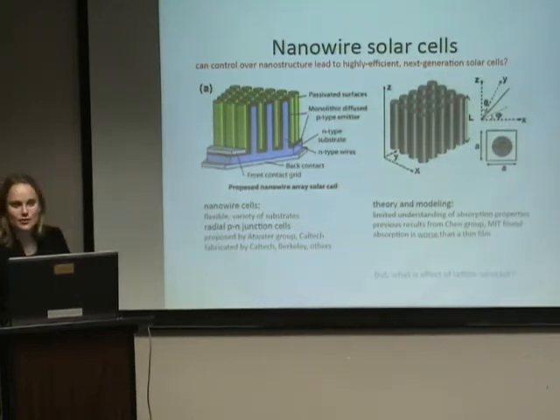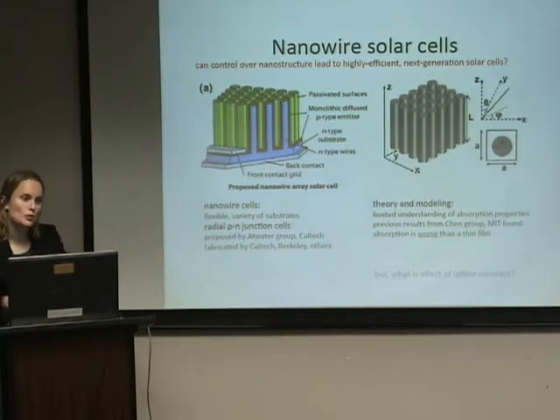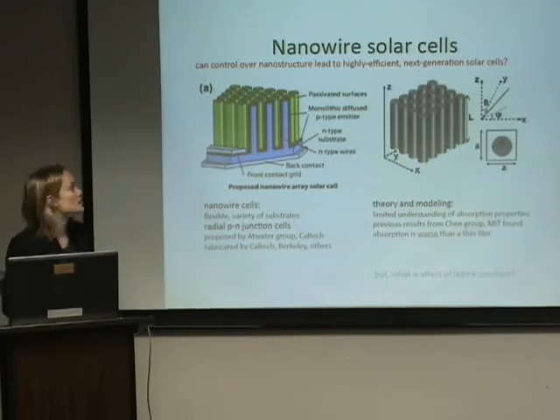However, the experiments that people have done to measure efficiencies so far are terrible, very low, way worse than any currently existing solar cells. So my interest here was in trying to figure out, okay, measured efficiencies are bad. That involves a number of different effects. The light comes in, the light has to generate electron-hole pairs, and then shown here in a color, that's a junction between a p region and an n region. That electron and hole have to be turned into a current. So there are a few different steps there, but we're going to focus now just on the optical absorption, the light coming in and generating electron-hole pairs, and try to figure out how that's related to the structure.